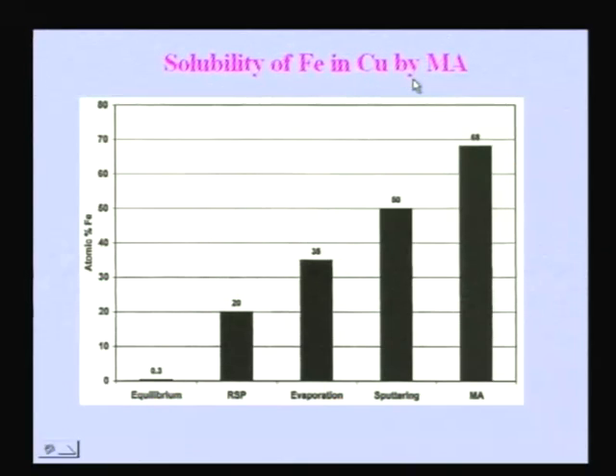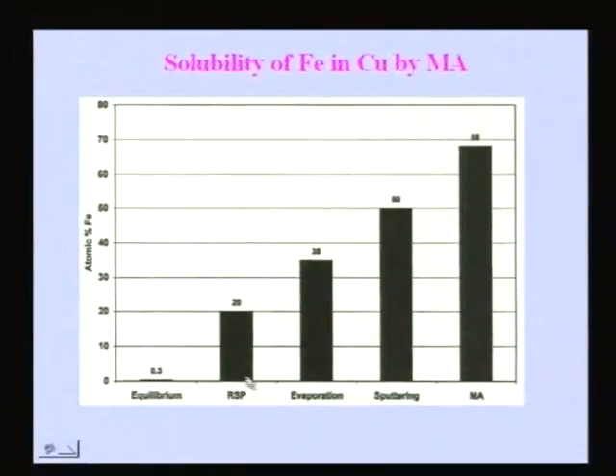This is iron copper. Iron copper is supposed to be an immiscible system. A lot of people are working on these immiscible systems now, particularly to put a small amount of copper into iron. In interstitial free steels, a lot of people want to put small precipitates of copper, particularly nanocrystalline copper, into iron, so that they can increase the strength of the steel. If you look at the equilibrium solubility, it is only 0.3%. Only 0.3% of iron can go into copper under equilibrium conditions. By rapid solidification one can go to 20%. By evaporation 35%. By sputtering about 50%. By mechanical alloying one can go to 68%.